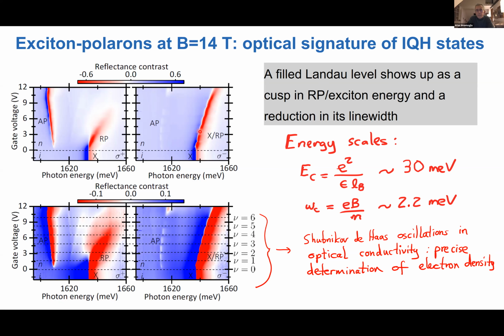integer quantum Hall states. And what we find is that, looking at the repulsive polaron in one polarization and the attractive polaron in the other, every time the electrons are in an integer quantum Hall state, there is a cusp in the exciton energy, and this is also associated with line narrowing. Now, we of course check these with the capacitive model. We actually have another way of determining the density, and we find that this agrees very well with what we expect from the capacitive model.